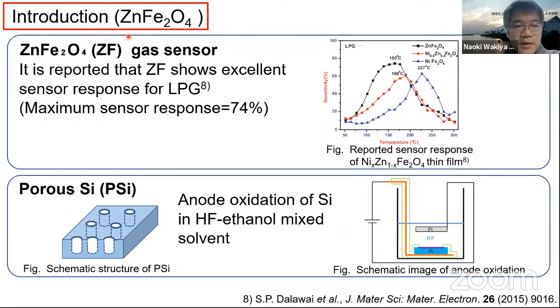And this is an explanation for the zinc ferrite. Zinc ferrite gas sensor shows excellent sensor response for LPG. This is the composition dependence of the gas sensor response with a zinc ferrite. This black is zinc ferrite, this blue is nickel ferrite, and this red is nickel zinc ferrite. So this data means that the peak point of the selectivity can be changed by changing the composition of the nickel zinc ferrite. And in this case, for zinc ferrite, the maximum sensor response is reported to be 74%.